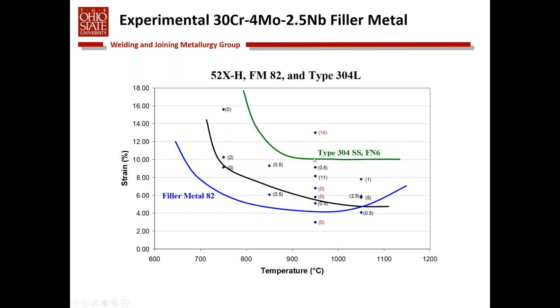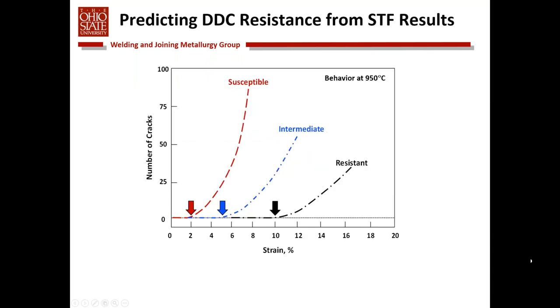And type 304, this is a different 52X material. This is a developmental filler material that we're interested in. 304 stainless steel, we know, is very resistant to this form of cracking, and its minimum strain is up around 10%. And so what we've learned from our DDC studies is when you get to minimum strains at 4% or less, material tends to be susceptible to cracking.